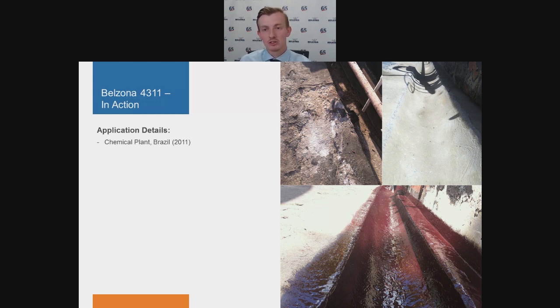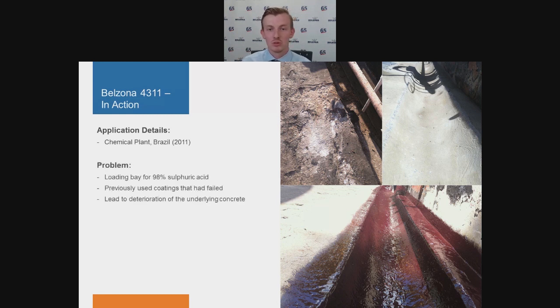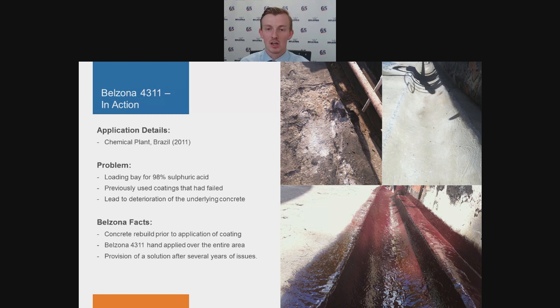And what was happening is that it was eating away at the concrete. Now, the asset owner had tried numerous different coatings prior to the Belzona coating, none of which were able to withstand the sulfuric acid for any prolonged period of time, and they were breaking down, and continually the concrete was becoming more and more deteriorated. So eventually the asset owner got in contact with Belzona, and we were able to clean the concrete, repair the concrete back to its original dimensions using our concrete repair materials, and then overcoat the concrete with the Belzona 4311 for further protection. This has now proven to be a much longer lasting solution than the previous solutions tried by the asset owner.